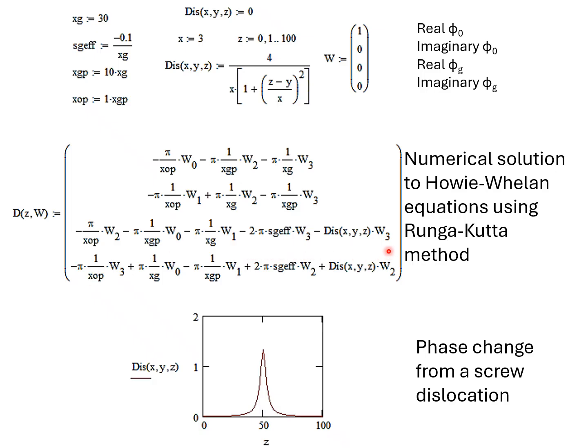These parts contain the effect of the dislocation. In this particular case, sorry, I've included a dislocation, and this is the equation that defines what the rotation of the dislocation planes, the effect of the strain from the dislocation has on the phase factor.